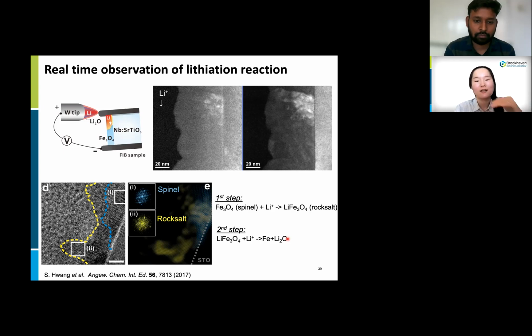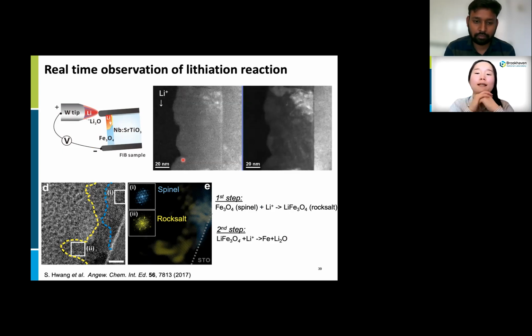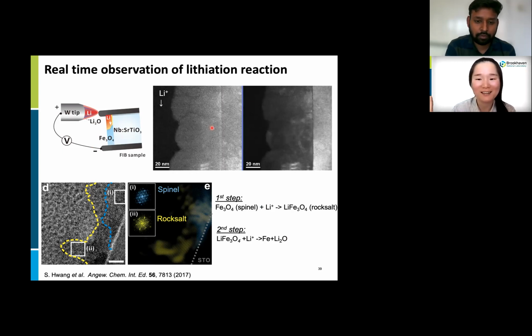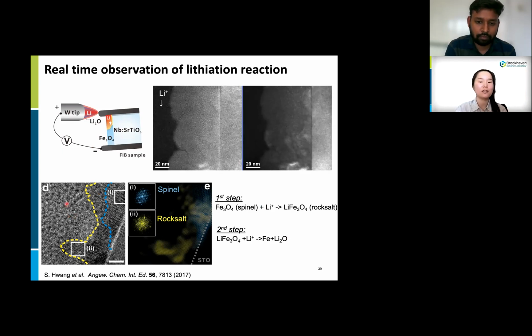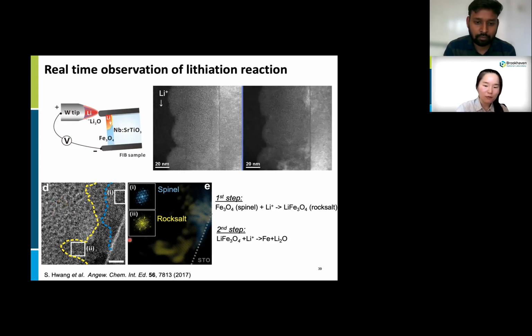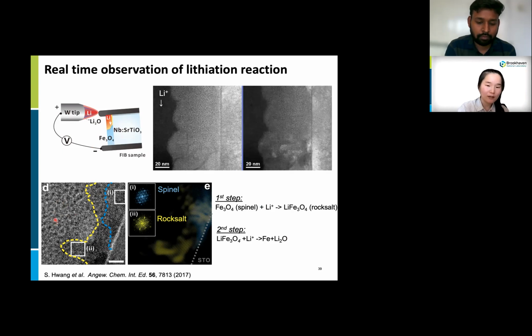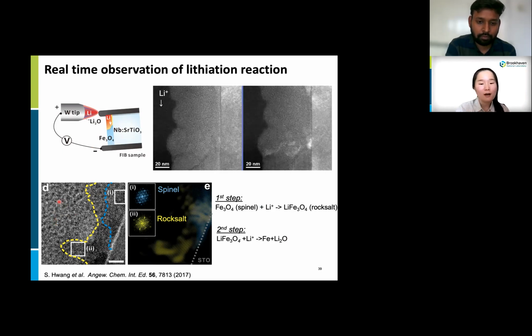When lithium ions are introduced from the top to the thin film, you may see the contrast change in the images, which means something is happening. And after getting this video, I got high resolution TEM images to figure out what really happened. The thin film far from the interface had already undergone the conversion reaction, but I found spinel and rock-salt phases near the interface, indicating that the strain from the interface delays the lithiation reaction.